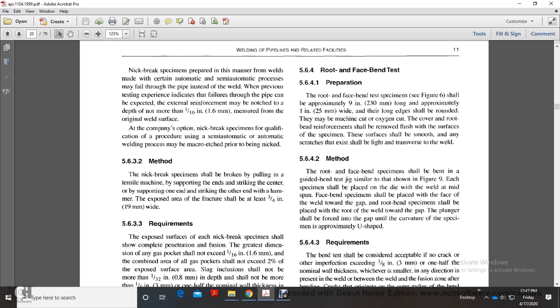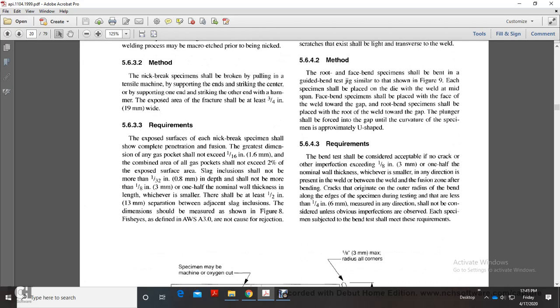The exposed area of the fracture shall be at least 3/4 inch. Requirements: the exposed surface of each nick break specimen shall show complete penetration and fusion. Any gas pocket shall not exceed 1/16 inch in greatest dimension, and the combined area of gas pockets shall not exceed 2% of the exposed surface area. Slag inclusions shall not be more than 1/32 inch deep and shall not be more than 1/8 inch or 1/2 of the nominal wall thickness long, whichever is smaller. There shall be at least 1/2 inch separation between adjacent slag inclusions. The dimensions shall be measured as shown in Figure 8. Fish eyes, as defined in AWS A3.0, are not cause for rejection.